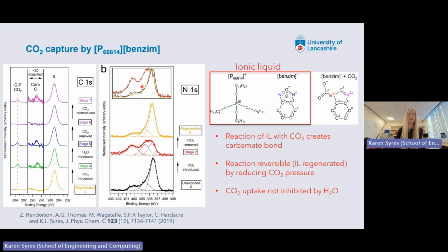So if you overlay them, you can see that the black and the yellow ones before and after the CO2 are pretty much the same. So what it showed is that we can actually reverse the reaction just by pumping the CO2 out, so that it's not a bond that you can't break. It forms this bond, and then we just pump the gas out and it comes back out again.